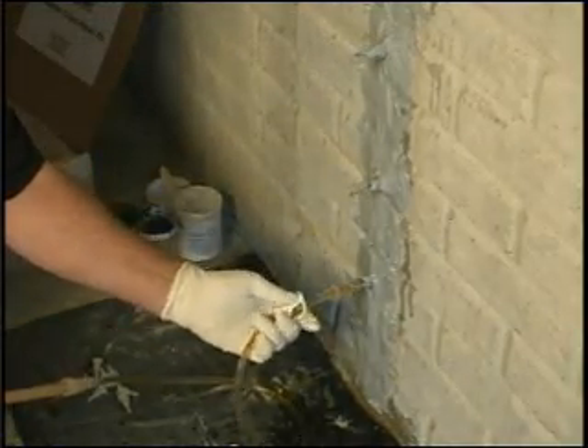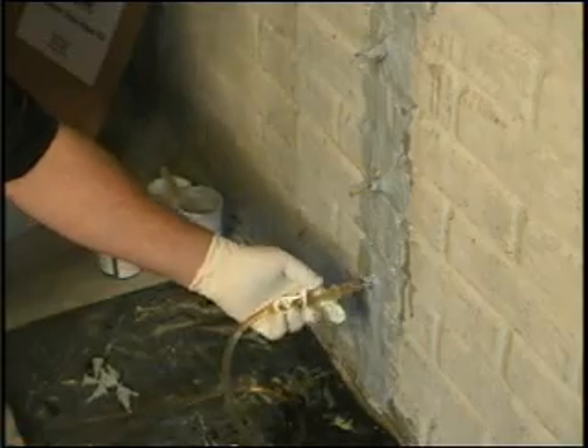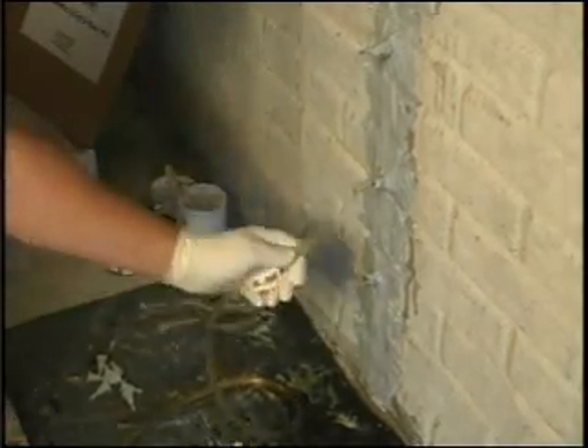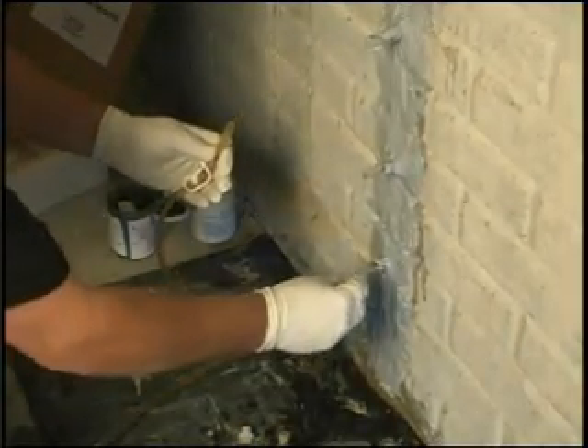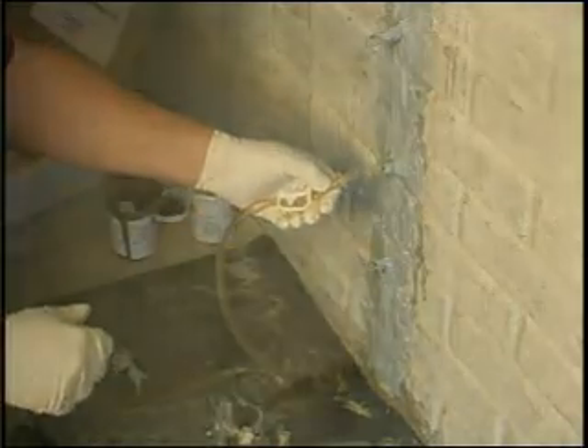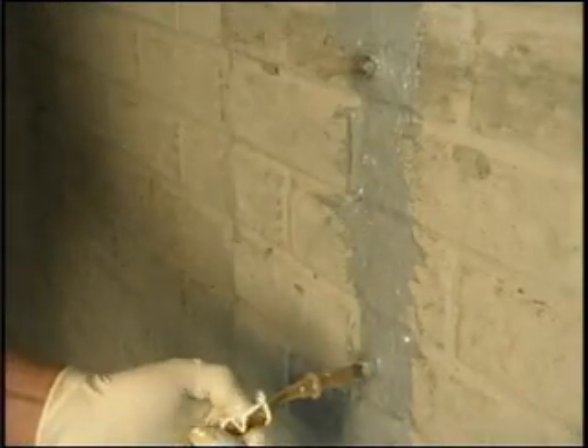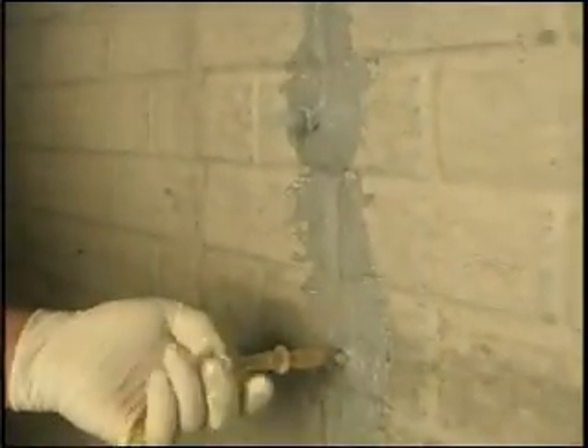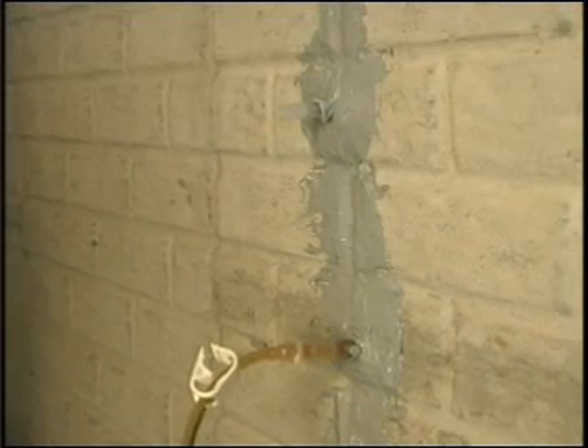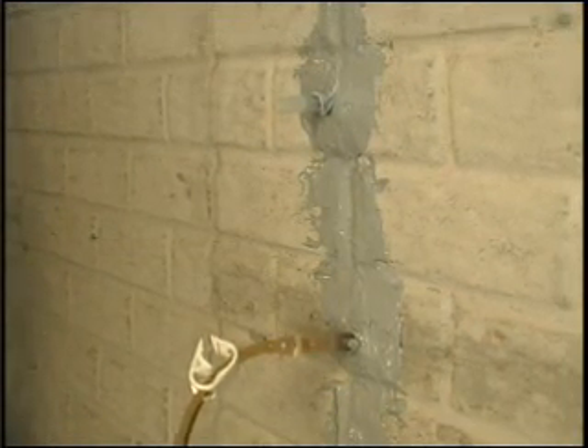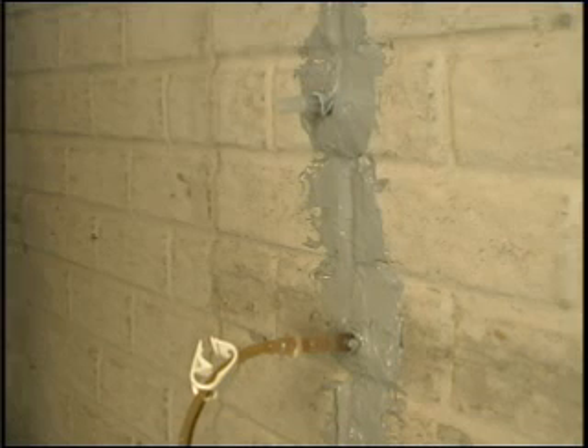Use the white plastic pinch valve on the hose assembly to turn off resin flow and remove the hose. Plug the first port with the cap provided and move up to the next port. Repeat this procedure until the entire crack has been injected with resin. Note, the secret to effective crack injection is patient, low-pressure introduction of the resin. Small or hairline cracks will require 3 to 4 minutes at each port for proper filling to take place.